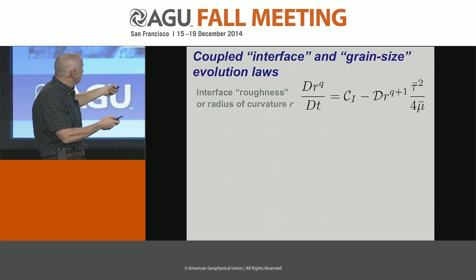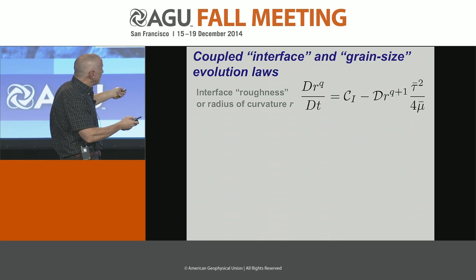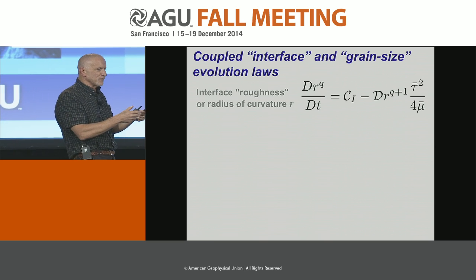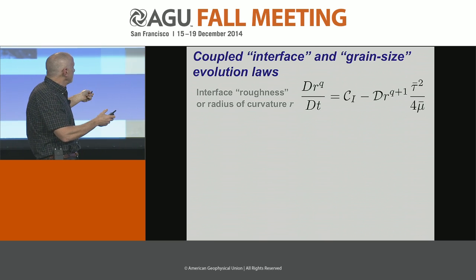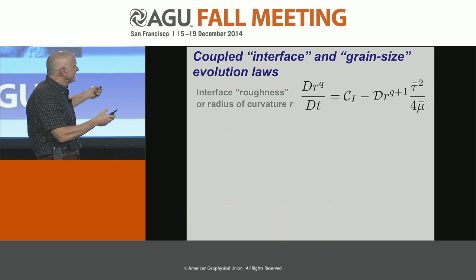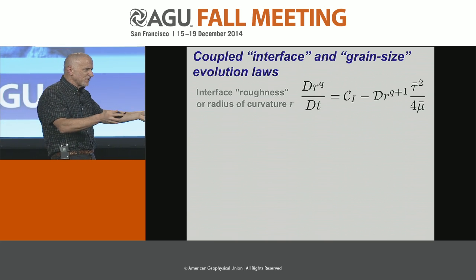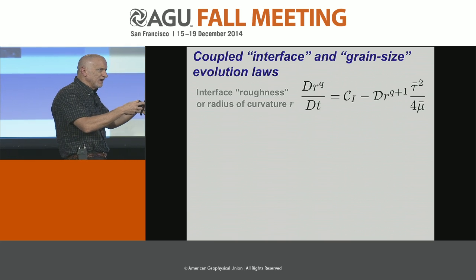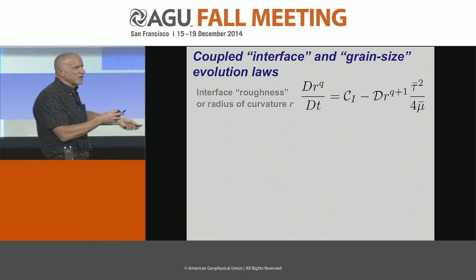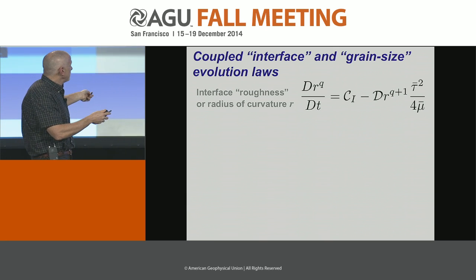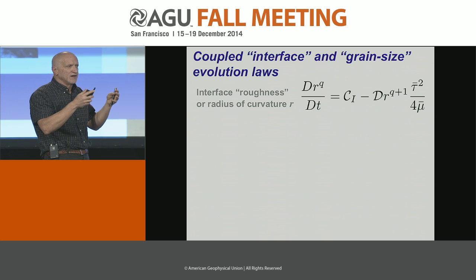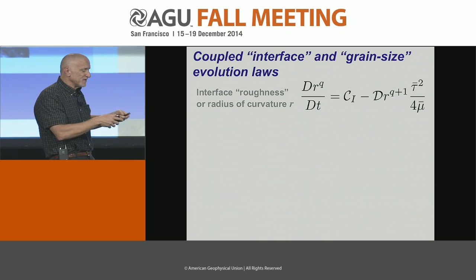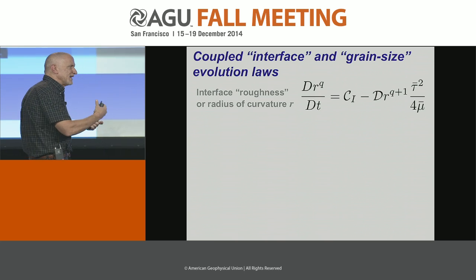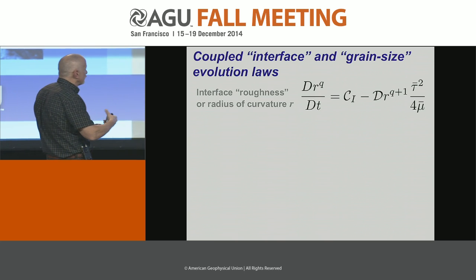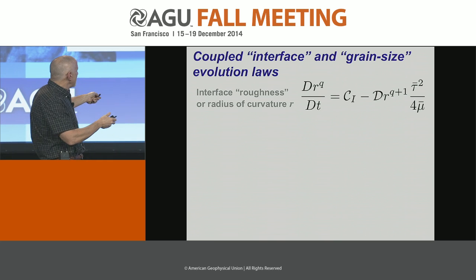In this particular case, when we're looking at the evolution of the roughness of the interface, or the radius of curvature of the interface, we're really looking at the competition between healing or coarsening, just standard as you let it sit, you'll go to a lower energy state and it will coarsen. So there's coarsening competing with damage, which is driven by work, by stress, that is basically trying to grind down the interface or stretch it and rend it and give it a higher curvature.